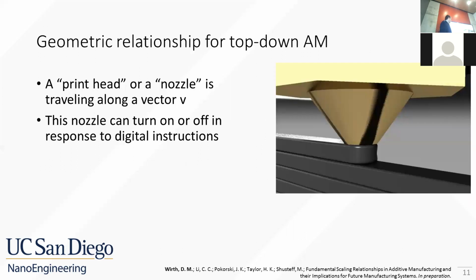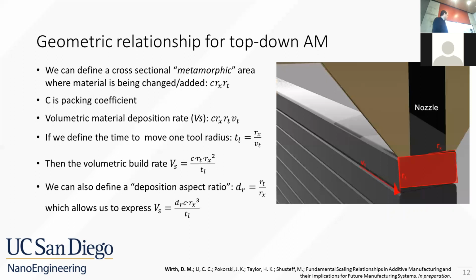So we can do this by looking at a notional additive manufacturing system, which is just an FDM nozzle moving along a vector, and this nozzle can turn on or off in response to digital instructions. Now, the absolute maximum rate that this printer can build an object is going to be with the nozzle always on. So using some more geometric constants of this system, in other words, the velocity that the nozzle is moving at, the layer height, radius of the nozzle, et cetera, we can develop an expression for the volumetric build rate as a function of these known geometric constants.